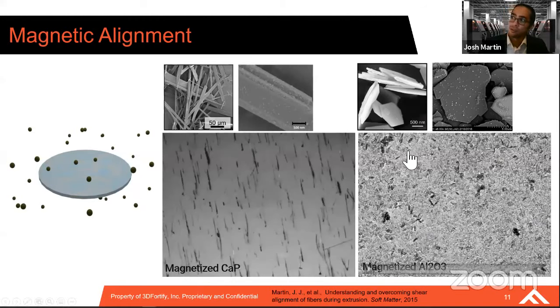One of the things that's unique about this technique is if you look at the fibers here, there's not a lot of magnetic material there. We're just peppering the surface of whatever additive of choice. Therefore, when you look at the bulk composites, like these parts themselves, they have less than 0.1% by volume magnetic material and exhibit no bulk response. So you could put these parts within an MRI and you would not exhibit any type of movement or magnetic moment, if you will.